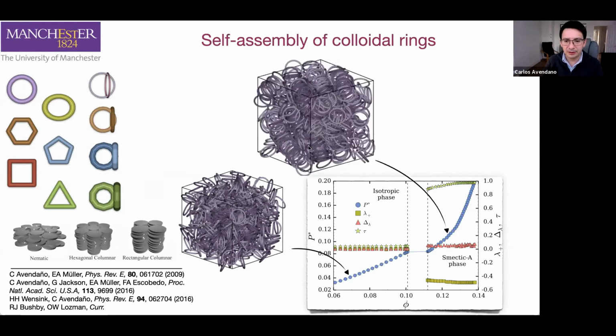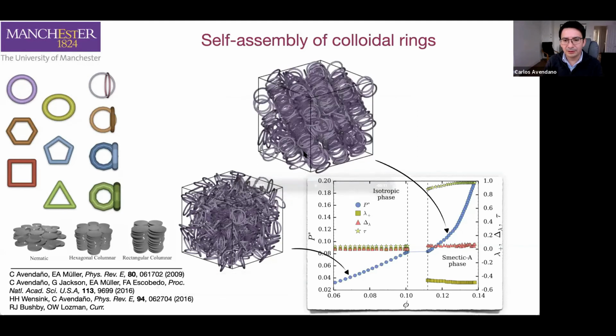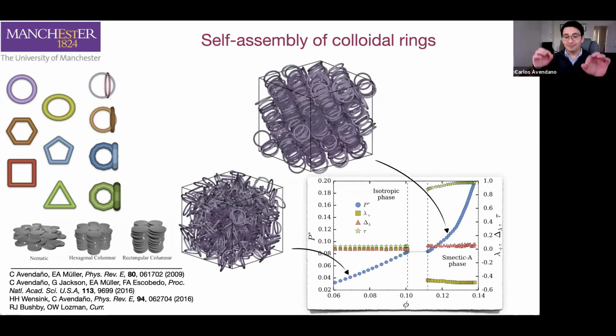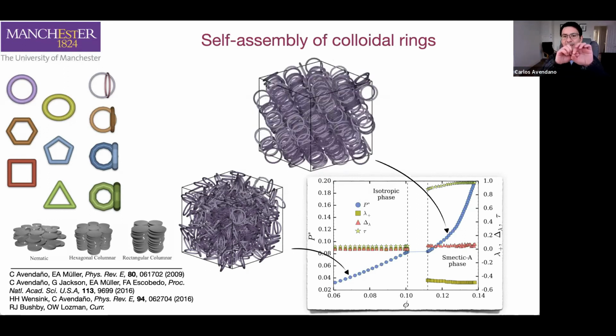So I'm going to let it run a little bit longer. And hopefully at some point you will see that the system starts forming layers. And in each layer, the rings start to try to interpenetrate each other. So what happens is that the particles will try to interpenetrate each other and they will get confined in a single layer. And essentially what they are forming is a smectic phase. But something very interesting with this smectic phase is if you look at the packing fraction that you obtain, the packing fraction for that smectic phase is about 10%. So we're talking about liquid crystals that have very high porosity. And again, that's a consequence of the non-convex shape of these particles.